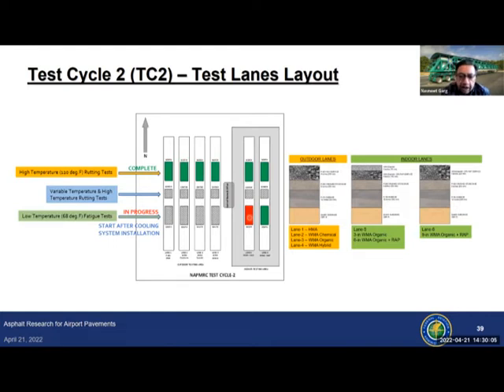So in lane 5, we started our testing at 72,000 pound wheel load, at higher wheel loads. We have completed about 60,000 passes. And again, we still don't see any evidence of cracking, or even any changes. Because once you have micro cracks develop, you start seeing increase in vertical stresses in the lower layers. We don't see any of that. And we have made a decision that we are going to test these lanes for up to 75,000 passes, because that's typically how many passes you would get on a major airport under these heavy aircraft, Boeing 777, in a 10-year period.